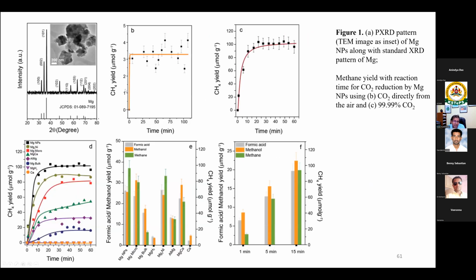This is called direct CO2 conversion. Look at the rate of the reaction: if I'm taking air, within a few minutes you convert all that CO2 into methane. If I take pure CO2, it takes around 10 to 15 minutes. Obviously, at this lab scale, you can clearly see this reaction is very fast. We carried out several other experiments to prove the mechanism.